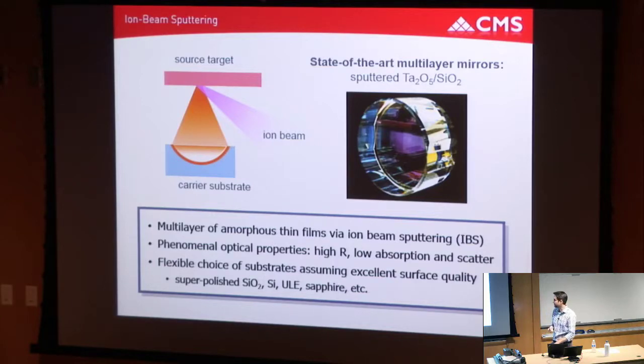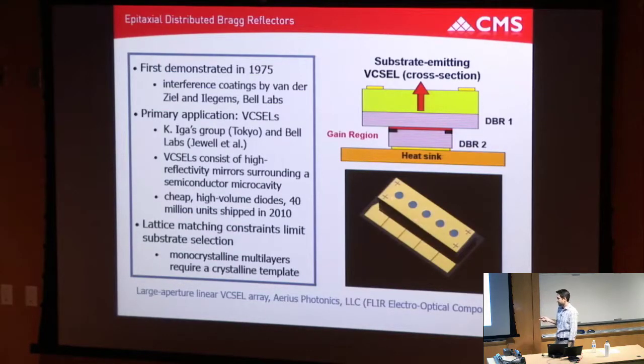for these low optical loss applications. About the same time in the mid-1970s, the first epitaxial interference coatings, or distributed Bragg reflectors, were developed. And this is, of course, like everything, at Bell Labs, Van der Ziel and Ilegems in the mid-70s, for these vertical cavity surface-emitting laser structures. And these are very interesting. There's a lot of work here on VCSELs, on these external cavity VCSEL structures. This is a microcavity laser with two Bragg mirrors sandwiching a gain medium. And this is all grown in one epitaxial growth process.